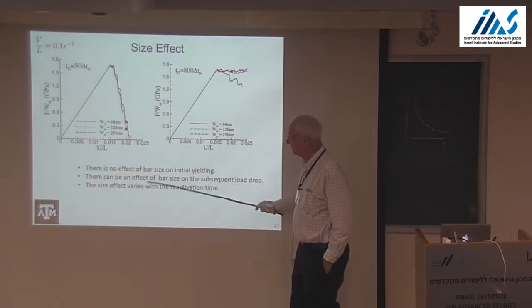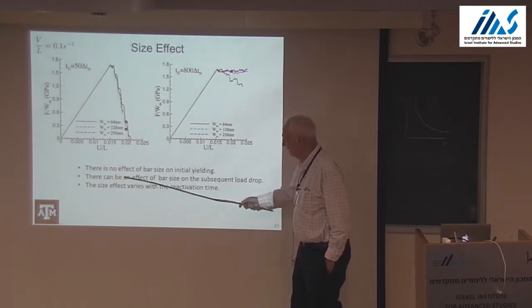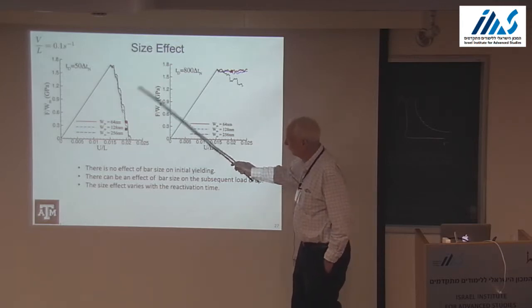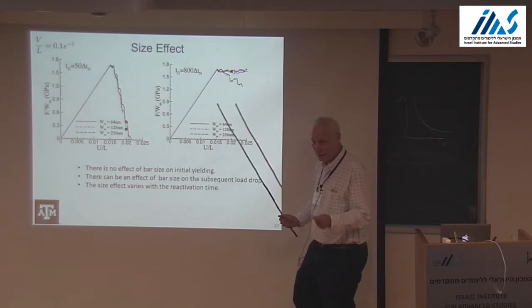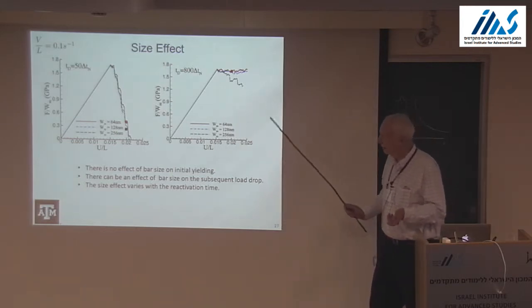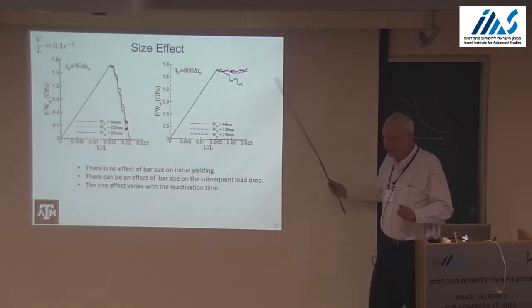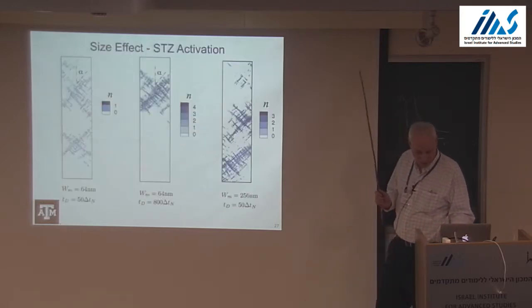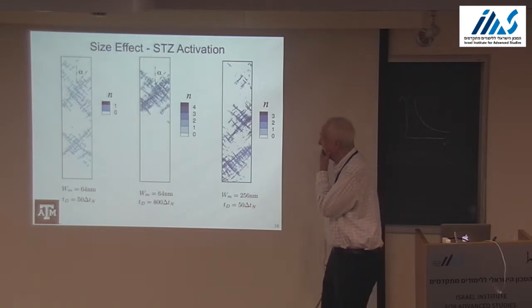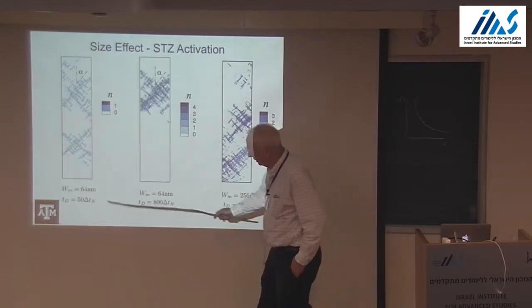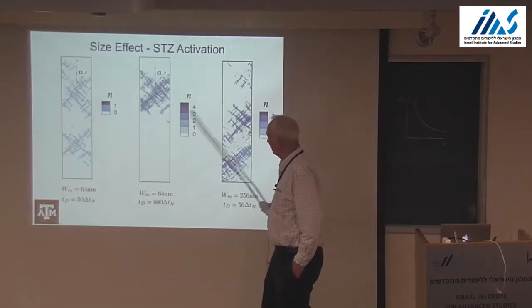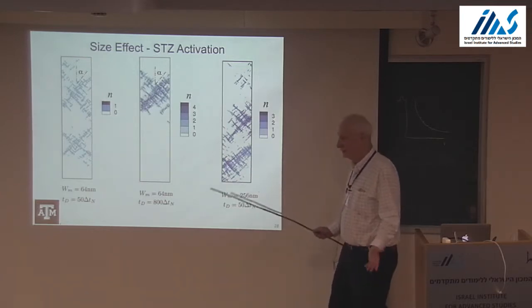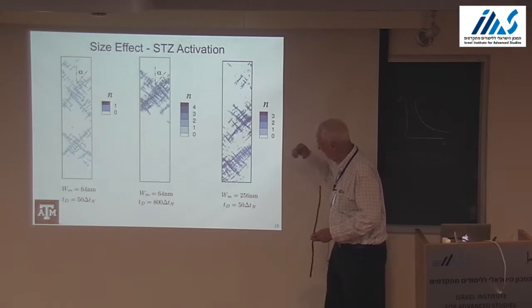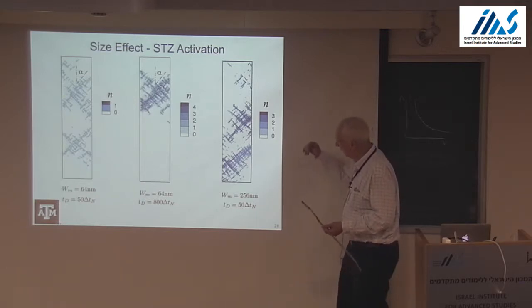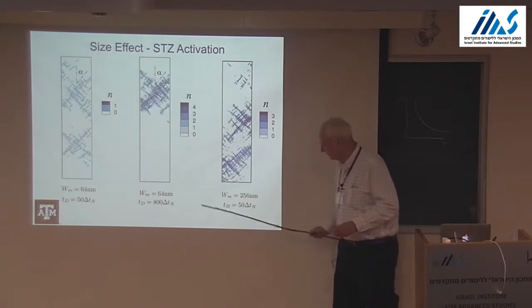So, of course, there's a size effect, and there's an effect on the load drop. And again, it depends on the time scale. At least our calculations indicate that the material time scale is very important for determining the size effect. Here you see a larger size, since you asked about the size effect. This is a factor of 4 in size. You see the shear band pattern varies with size. You get more shear bands in larger specimens.